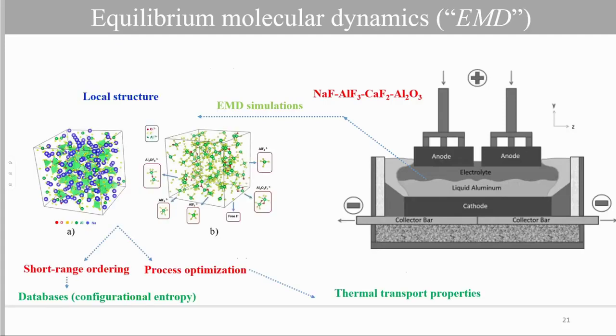We can also calculate the local structure. Having good information of the local structure - here in this case the local structure consists of free sodium, free fluorine, and coordination complexes which are basically fluoroaluminate and oxofluoroaluminate - this is very important. The knowledge of local structure in the melt is very important, first to represent the short-range ordering within the system so that we can represent more accurately the entropy of mixing, and also for a better description of the thermal transport properties of the electrolyte.